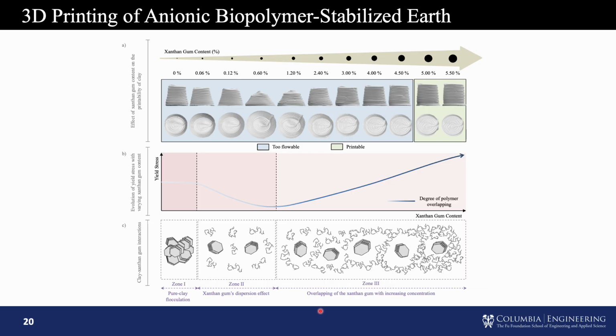Let's put all of these results in one figure. For this figure, I used xanthan gum, which works pretty much the same as sodium alginate. Both of them are anionic biopolymers and they're non-binding. Okay, so at the beginning, when we only have clay in the system, clay naturally flocculates and creates some kind of microstructure, which has some degree of yield stress, right? It's not the perfect material to print, but you still see some degree of buildability. Then you try to add some anionic biopolymer that does not bind to clay. Because both the anionic biopolymer and the clay are negatively charged, they're going to have a very strong electrostatic repulsion force, which will prevent the clay's flocculation.